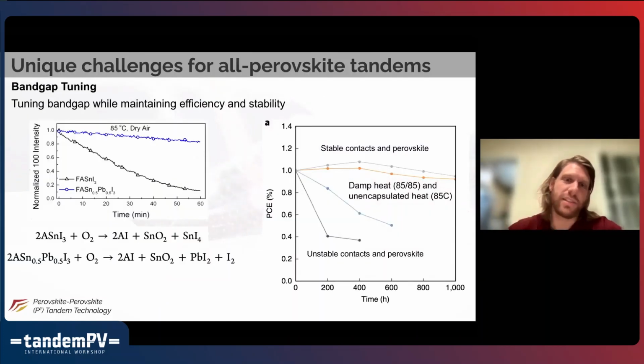Specifically to all perovskite tandems, there are some challenges associated with deviating from the standard 1.5, 1.6 eV band gap and going to the lower band gaps. Now you have this extra challenge with stability, especially when there's tin in the perovskite. We've previously shown that the exact composition is really important in determining the stability of tin-based perovskites. So if you have half of the B site being lead, you actually completely change the oxidation mechanism for the low band gap perovskites. And this was published a few years ago.